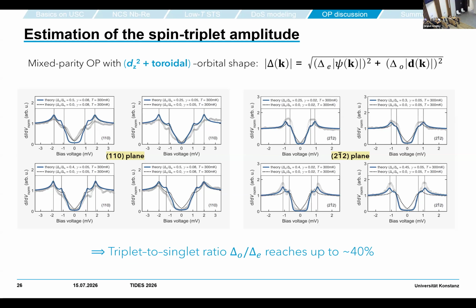I should make one remark: the assumption we made is that the total order parameter can be described by the square root of the even component on the scalar wave function squared, plus the odd component projected on the vectorial component squared. There is a simplification—we neglected all interference terms.